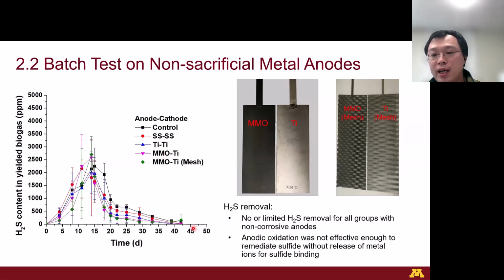Unlike the sacrificial anode, these materials did not release metal ions for sulfide precipitation at a low voltage. The results showed that none of these non-sacrificial anodes effectively removed hydrogen sulfide from manure. So we can say that anodic oxidation alone, without metal sulfide binding, was not strong enough to reduce the sulfide release from manure storage.